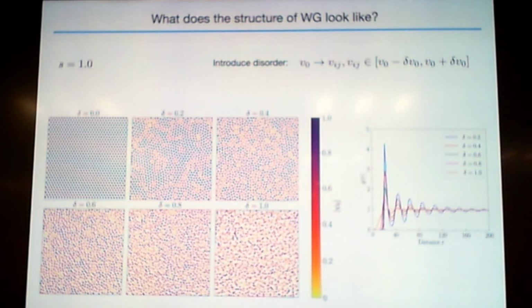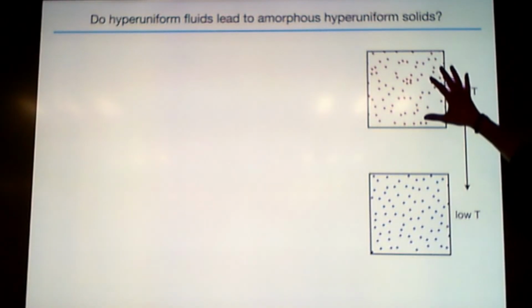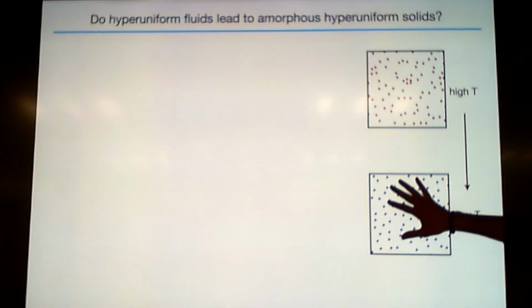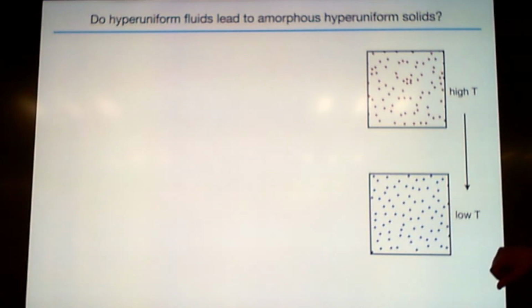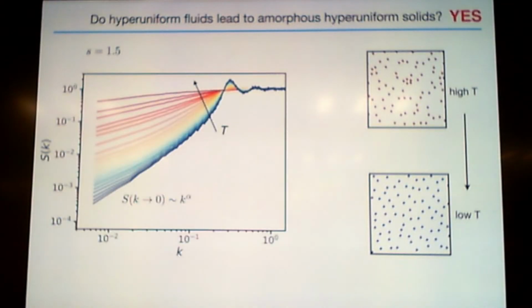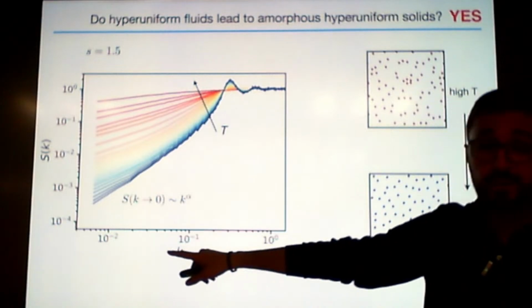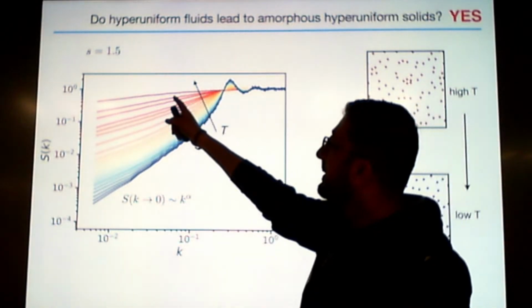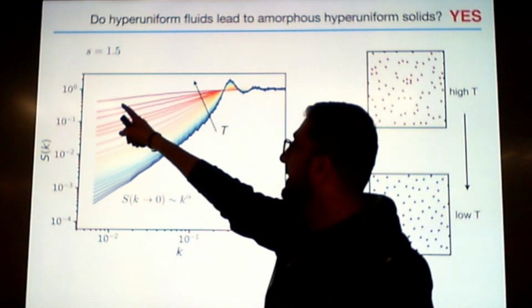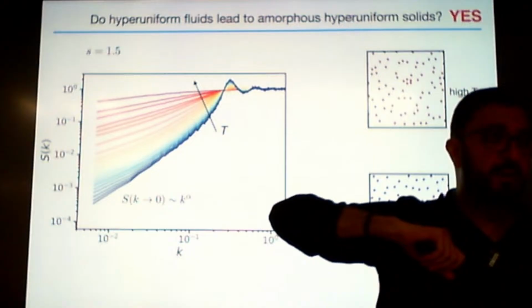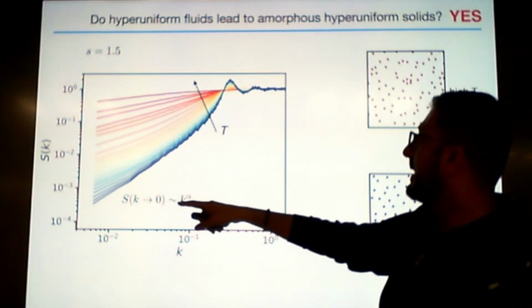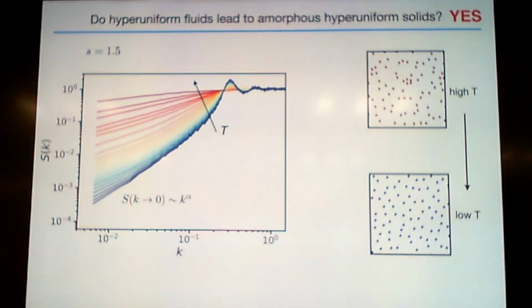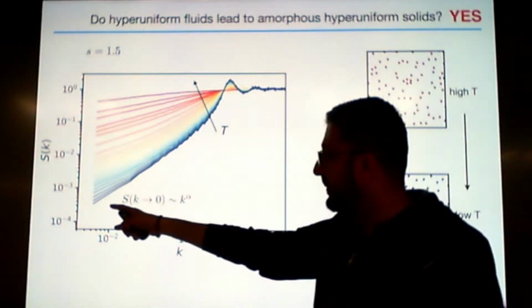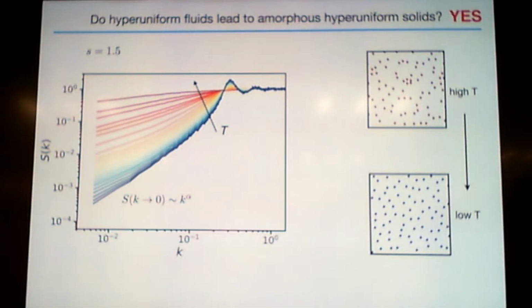Now the question here is, we know that this is hyperuniform, okay? And we freeze all the way to 0 temperature. Does it stay hyperuniform or not? So is hyperuniformity still conserved by the glass transition? Well, I wouldn't ask this question if it wasn't, right? The answer is yes. This is the structure factor versus the wave number k. This is a log-log scale, even though it looks like it's not hyperuniform, it goes down very slowly to 0. And as the temperature is decreased, you're suppressing more and more the fluctuations. And interestingly, these fluctuations even survive the glass transition. They are even becoming more hyperuniform, measured by alpha. I will show you in a minute. Quite interesting.